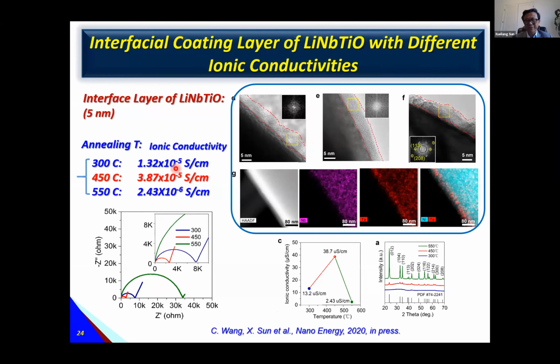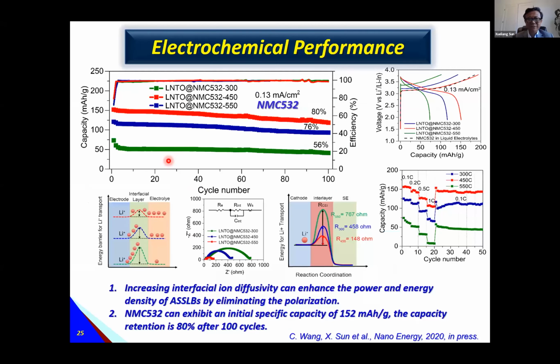So we simulate the battery to compare the ionic conductivity at the interface, and how big the difference in performance is. You can find that if the ionic conductivity at the interface is low, the capacity is low. If the ionic conductivity is higher, the battery maintains very high performance. The reason is that the barrier here is very important for lithium transport, and also for leakability. So this demonstrates that ionic conductivity at the interface is so important.